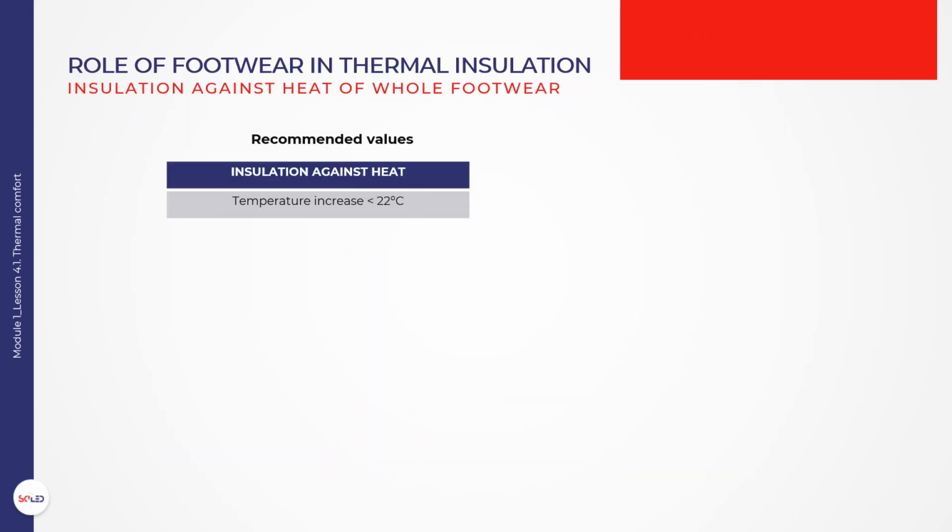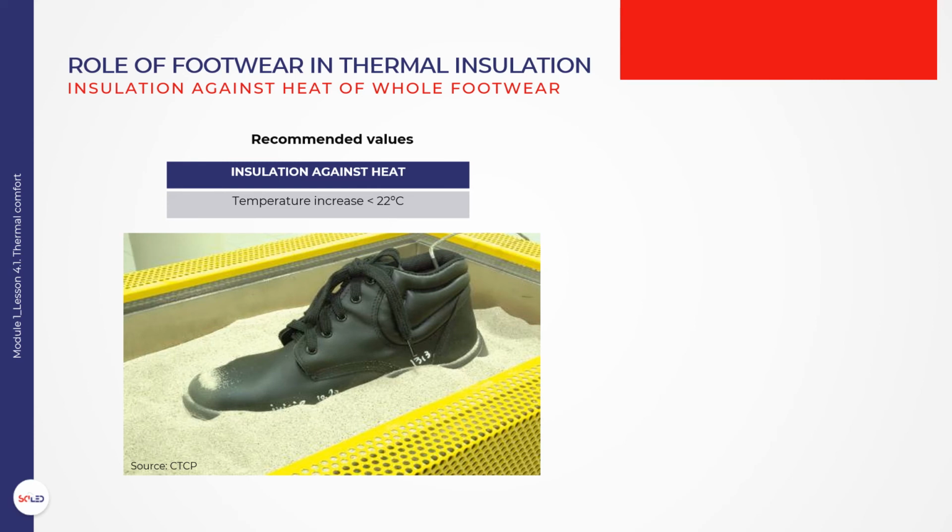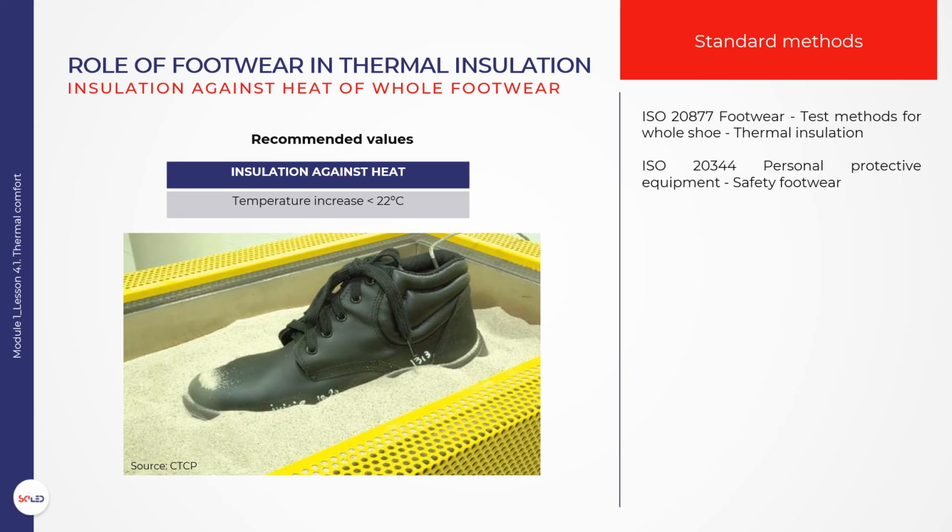In this test, the footwear is placed on a hot plate at a very high temperature, for example 150 degrees Celsius for 30 minutes. The temperature sensor inside the shoe on the insole records the temperature increase. The increase in temperature on the surface of the insole after 30 minutes should not exceed 22 degrees Celsius. This method is described in ISO 20344 and ISO 20877.